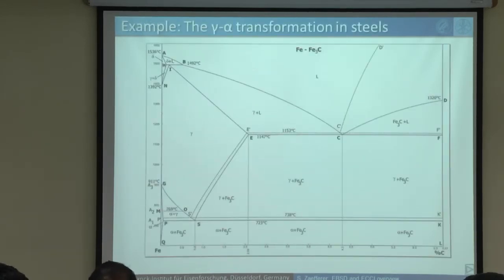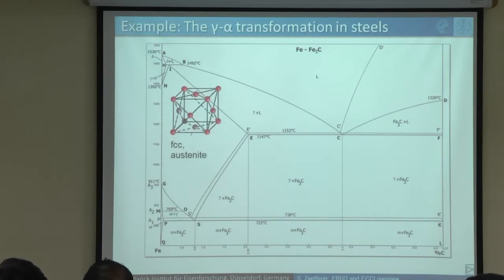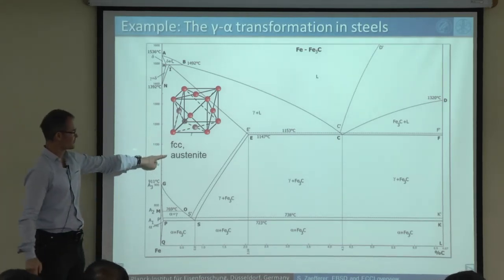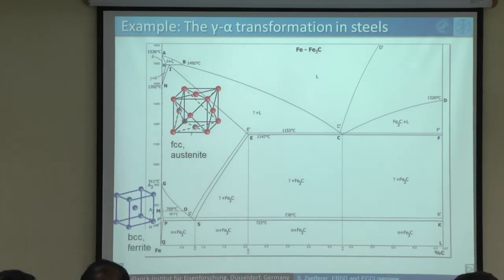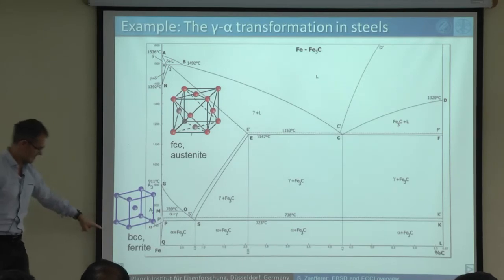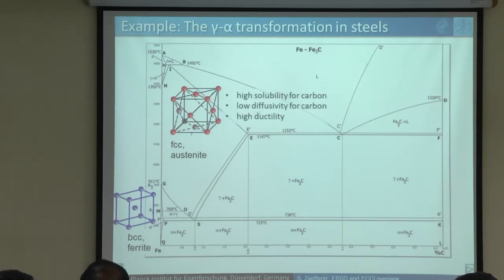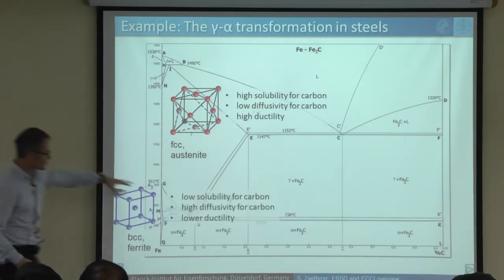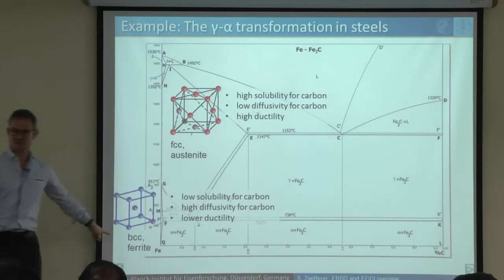So you all know, I believe, the iron-carbon phase diagram, and we're keeping it simple for the moment. We're just saying the major thing in the simple iron-carbon phase diagram is that there is a high-temperature structure, which is called austenite, and it has an FCC structure, and there is a low-temperature structure, which is called ferrite, and it has a BCC structure. And actually, they are very, how should I say, inversely behaving phases. Quite amazing. So this one here has high solubility for carbon, but low diffusivity for carbon, and high ductility, while this one here has low solubility for carbon, high diffusivity for carbon, and low ductility.